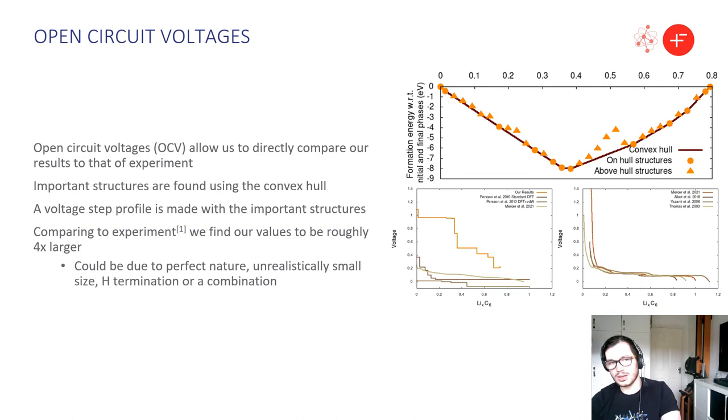Comparing to experiment we find our voltages to be roughly four times larger. This could be due to the perfect nature of our nanoparticle, it being unrealistically small, and or using the decision to use hydrogen termination or some sort of combination of all of the above.